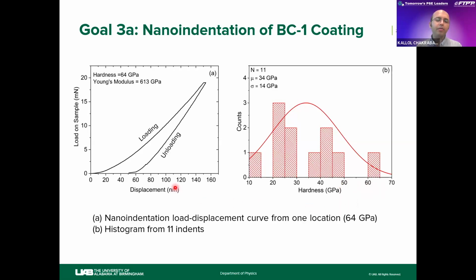In the left panel, we have plotted the load versus displacement curve. This is the loading curve when the indenter was hitting the sample, and this is the unloading curve. From the loading and unloading curve, we can see that most of the deformation is elastic deformation, and only 25 or 30% is plastically deformed. That's why we also know that this material is super hard.